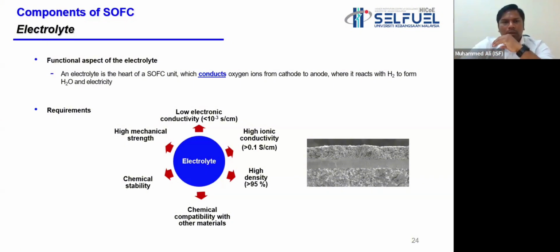So this particular electrolyte material should have low electronic conductivity. That means 100% insulating material. As long as it is purely insulating material, it's good. And also it should have high ionic conductivity so that we can reduce the ohmic resistance.